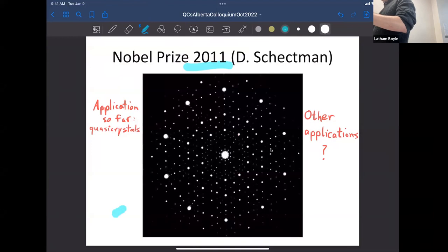Okay, and the thing that's strange about this diffraction pattern is that if you count the number of dots in a ring here, you'll see there's 10 of them actually. So this diffraction pattern has a tenfold symmetry, which should be forbidden for a crystal. In other words, it had normally been thought that if you have a diffraction pattern that forms these bright Bragg diffraction peaks, that was the sign that you were looking at a crystal. But now we have a crystal, quote unquote, that seems to be showing a symmetry to its Bragg diffraction pattern, which should be forbidden by the theorem that I mentioned on the second slide. In other words, we should only be able to see Bragg diffraction patterns with twofold, threefold, fourfold, or sixfold symmetry. Instead, we're seeing tenfold symmetry.